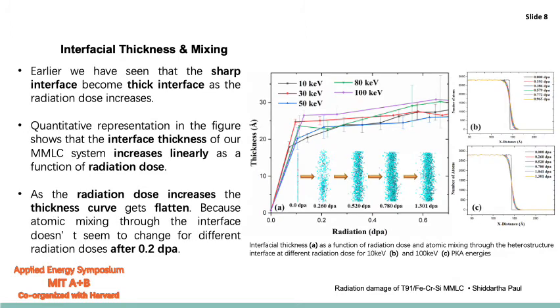In the earlier slide we have seen from the structural evaluation that the sharp interface actually gets thicker. So this figure supports this visual analysis with a quantitative representation of the interface thickness as a function of the radiation dose. We can see that as the radiation dose increases, the interfacial thickness also increases kind of linearly at the very initial dpa, but after 0.2 dpa the interface thickness gets saturated. So that's why the curve gets flattened in this case.